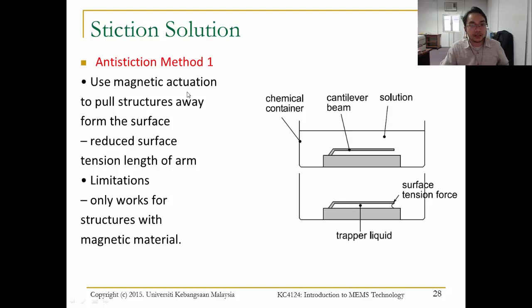is by using magnetic actuation to pull structures away from the surface. This can be used to reduce surface tension length of arm. Alright, the limitation is it only works for structures with magnetic material. For example, if the cantilever beam is magnetically sensitive, we can use magnetic actuation to pull it up, to make sure that it does not stick to the substrate. But the limitation is that for other types of material, we cannot use this method.